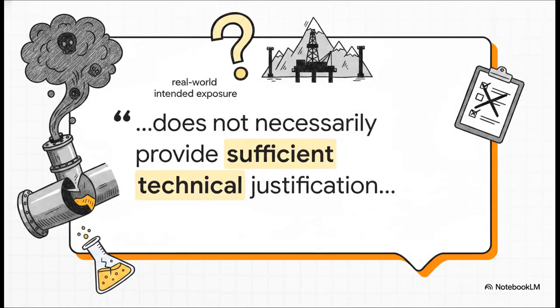But as this vital warning from the specification reminds us, simply passing a baseline stress test doesn't automatically mean the pipe is invincible. This is a super crucial note from Annex H. The engineers writing this code are explicitly stating, don't get complacent. Just because your pipe survived a baseline WAB test at 72% of its yield strength doesn't mean it's ready for the most unpredictable, severe, sour regions. It's there to push engineers to constantly evaluate the specific real-world exposure they'll face, rather than just blindly checking a box on a form.